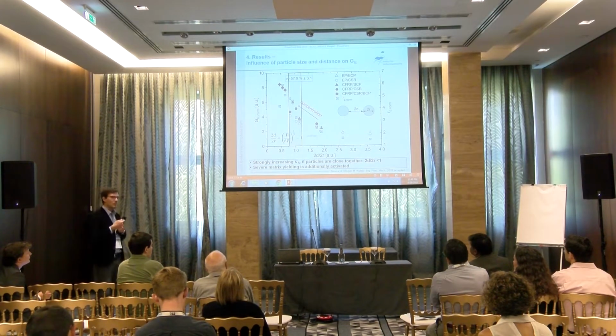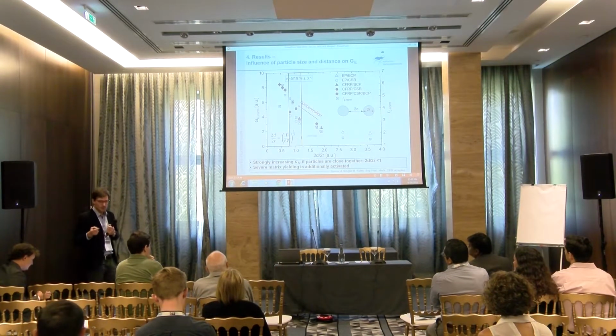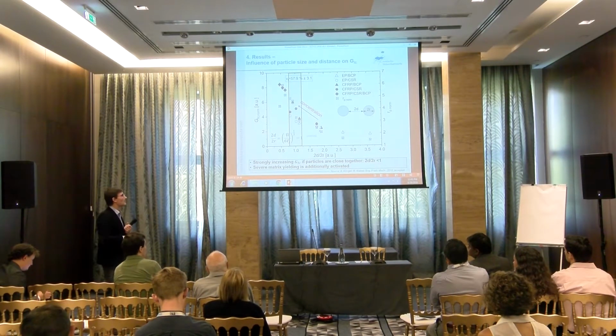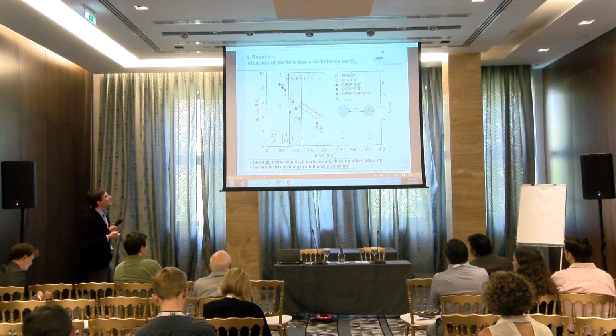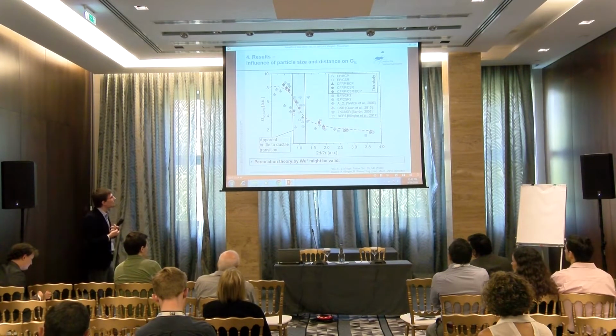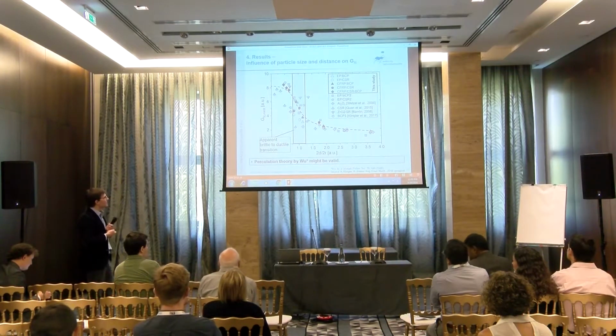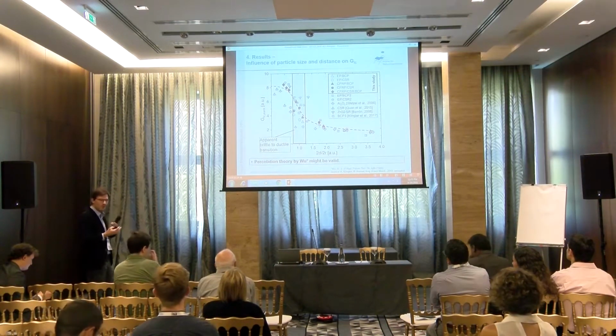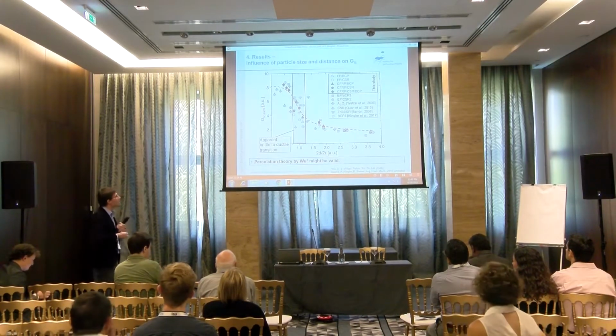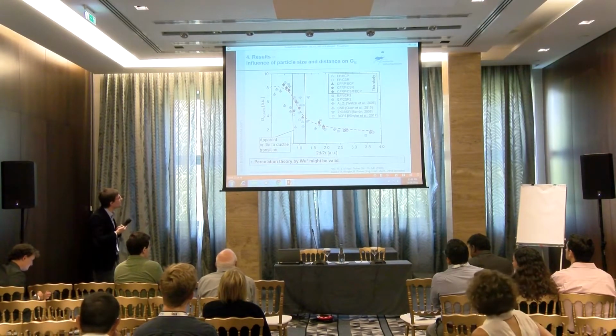What you probably do is change locally, in between the nanoparticles, your state of stress from a plane strain condition to a plane stress condition, which, additionally to making use of the particles in terms of cavitation and so on, lets you make use of your matrix by allowing the matrix to yield. Interesting was that when we added some more data from the literature, we followed a similar trend, right? And there is a percolation theory by Wu, which more or less explains this behavior. And we can see that even in our CFRP.